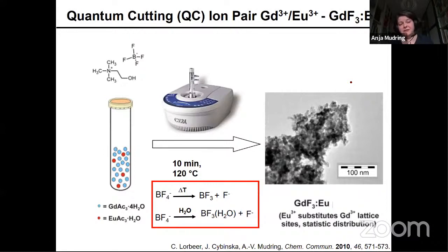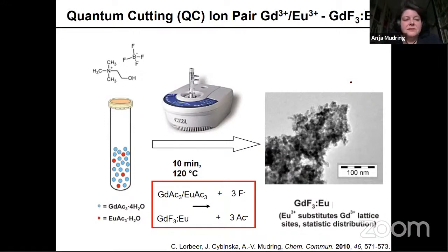BF4 decomposes and releases fluoride. And the fluoride immediately reacts with the rare earth ions and gadolinium fluoride doped with europium precipitates, and you obtain it as nanoparticles. To the right, you see a TEM image, it looks ugly because now you have something that can release fluoride, and that's not smart to put into a TEM. It's probably a one-time experiment. So when you wash the ionic liquid away, the particles agglomerate, but again, you can redisperse them and you get finely dispersed nanoparticles, which are about 5 nanometers in diameter.